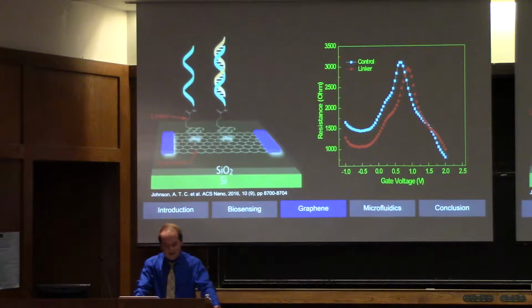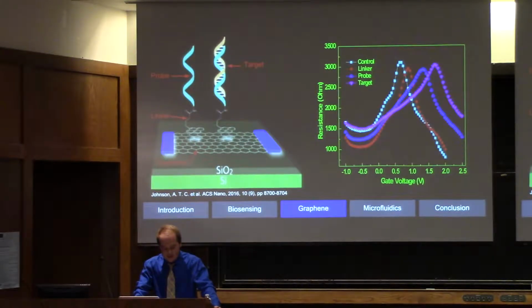We then add the linker to the sample, and we immediately notice a shift in the Dirac point in our graph. This lets us know that the linker has successfully bonded. We can see the same type of shifts when we add the probe and subsequently the target DNA. The measurement of the target is the most important, because if we see a shift here, then we can pretty much assume that the DNA has bonded to the probe and to the graphene.